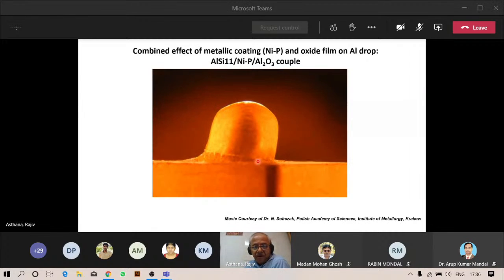In this case, if you were not careful enough, you would measure an incorrect contact angle because this oxide skin is preventing the liquid to spread out fully. So in reality, we are looking at aluminum silicon on this coated alumina substrate, and that is wetting the solid surface. But the shape of the droplet tells you that it's a non-wetting system, which is not correct. So the oxide skin on the metal is causing a lot of problems.